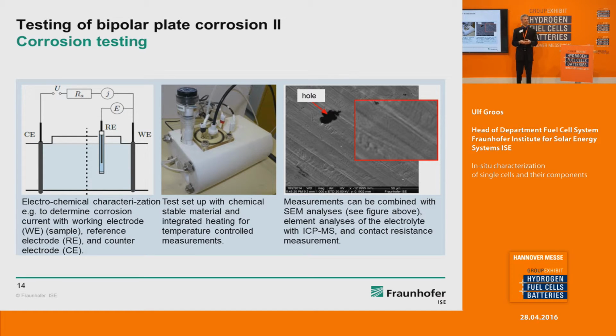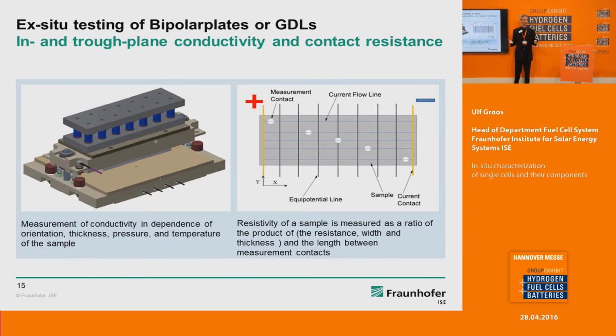Corrosion might occur in the metallic bipolar plate, so corrosion testing of metallic bipolar plates is an issue. One method which is often applied is measuring the corrosion current over time, so we have a setup for that. And of course, the conductivity of your bipolar plate is very crucial. So we developed in-house a measurement setup for measuring the in-plane and the through-plane conductivity of metallic bipolar plates. Especially the through-plane conductivity of very, very thin samples, like metallic bipolar plates with a thickness of 100 microns and below, is very tricky. So we had to develop something in-house, as it's not available commercially.